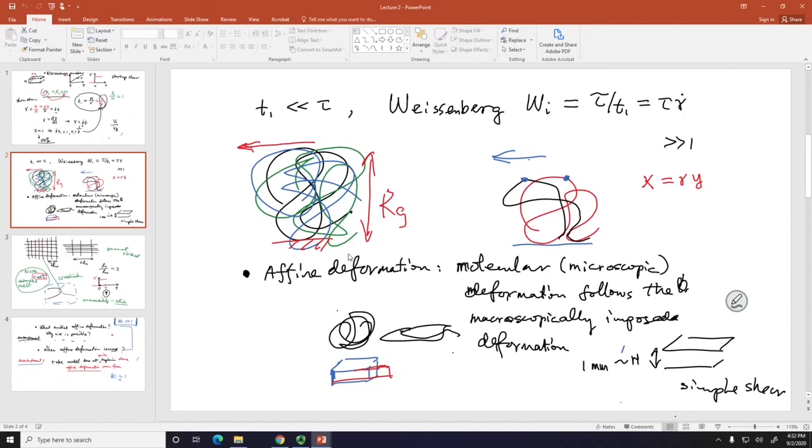So we talked about, let's recall, I took a very slow pace telling you the meaning of the Weissenberg number, essentially involving a ratio. The meaning of it: if moving one h to the right takes negligible time compared to tau, in other words, within tau I can move 1,000 h to the right, that's Weissenberg number equals 1,000. And I indicated that is the limit.